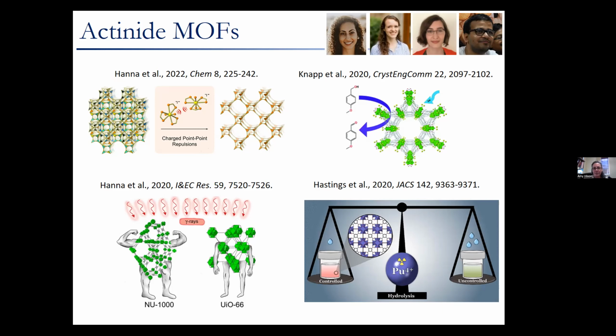But anyway, what she found is that the NU1000 was really resilient and there was no noticeable breakdown of the metal organic framework regardless of the dose that it received, whereas the UIO66 under the low dose rate had some significant decomposition. So this leads us to believe that the more chronic lower dose rates might be more destructive to these compounds.